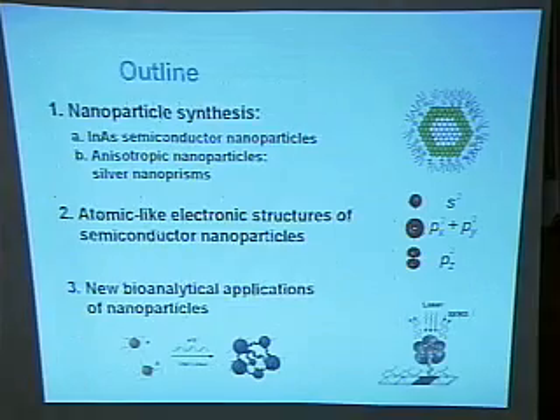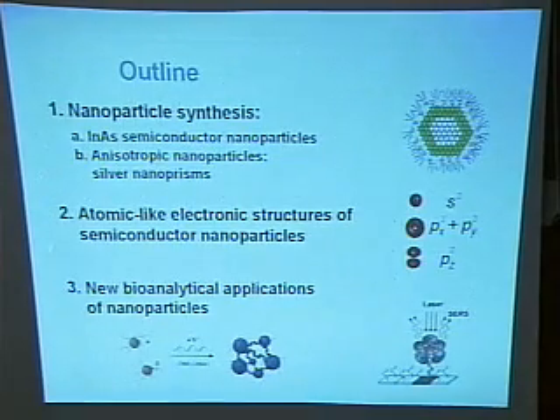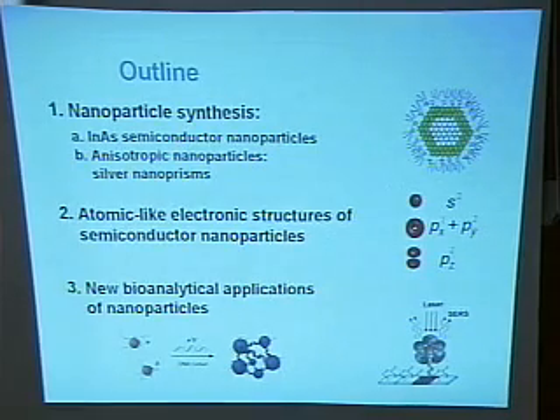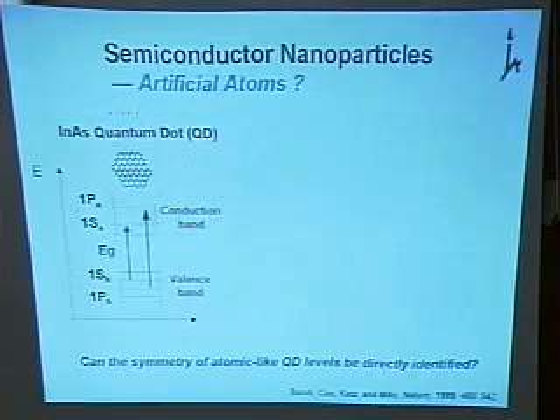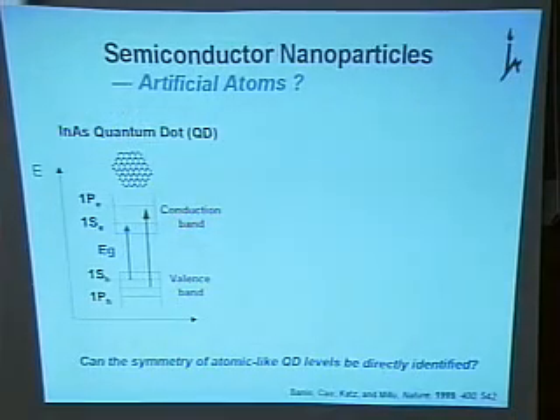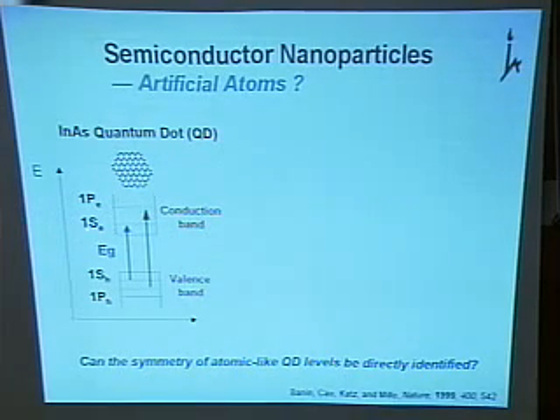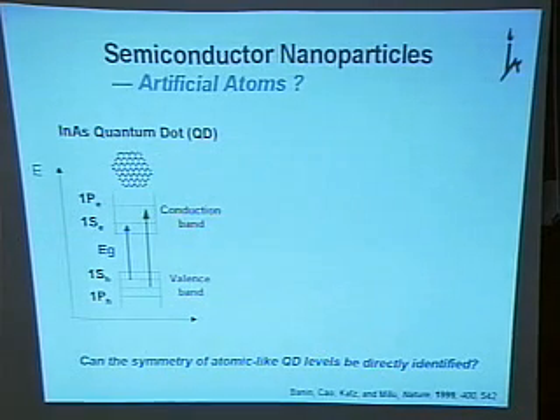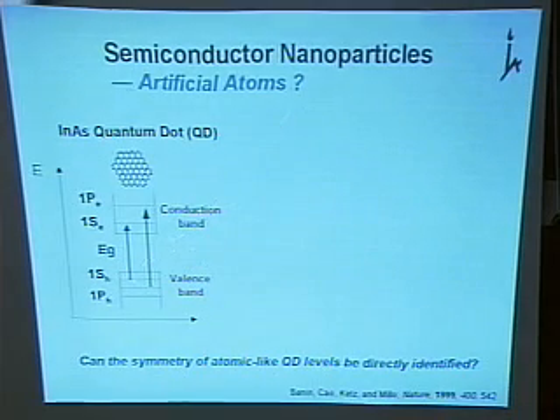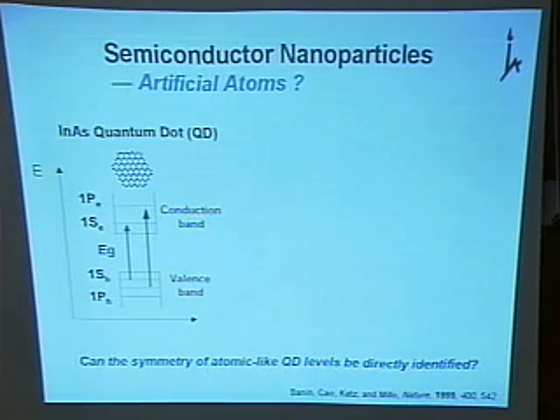So this is where I finish the part about particle synthesis. In the next part, I'm going to talk about atomic-like structures of semiconductor nanoparticles. For semiconductor nanoparticles, this goes back to the 1980s, from early theoretical work carried out by Louis Brus. He predicted that these semiconductor nanoparticles have separate electronic states with narrow transitions, and these states have S and P character. And later, optical work proved that they do have separate energy levels and narrow transitions. However, the optical measurement could not directly give you the symmetry of these states. You don't know exactly if it's S or P.